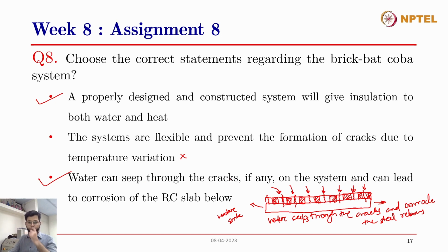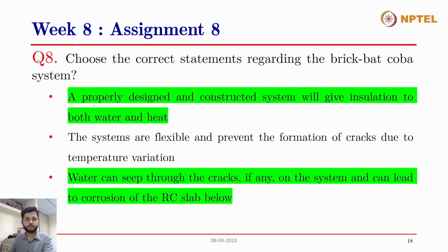So therefore, these are not flexible systems, and rather they allow for the formation of the cracks, or they accelerate the formation of the cracks as they are rigid. So they don't move along with the temperature variation, and therefore they can allow for the creation of these cracks, and these cracks can allow for collection of the water inside the bricks, which can further accelerate the corrosion process in the RC structure below. So the last one is a correct statement as well.